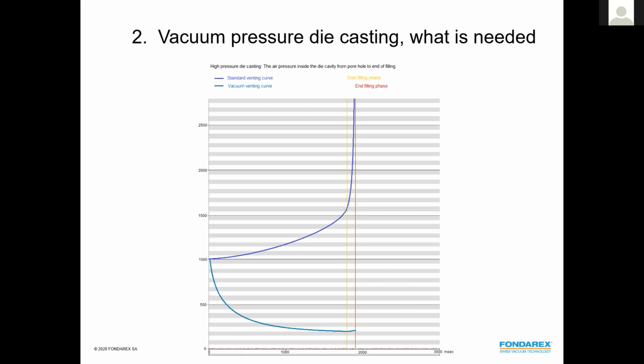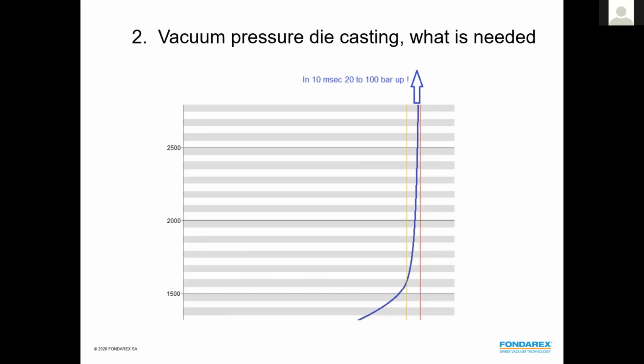Now, looking at the structure to see what the difference is. Without vacuum, the pressure always increases. With vacuum, we try to get basically no air inside the cavity. Looking a little more precisely, without vacuum, everything is controlled up to the filling phase. But at the very end of the filling phase, the air is entrapped, and most of the time we cannot even bring all the air and gas out. It is somewhere entrapped in the alloy, and it will go up to 10, 20, up to 100 bars at the very end of the filling.